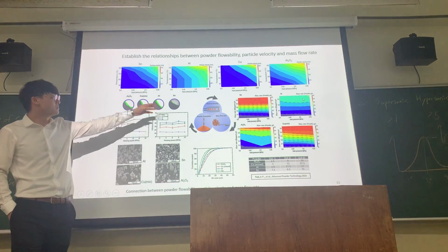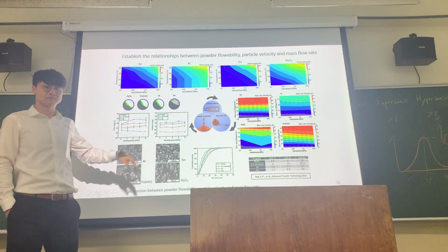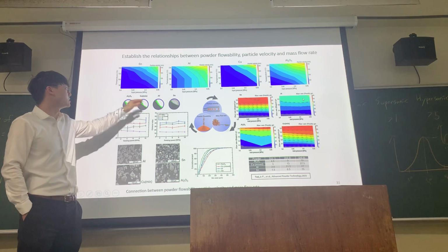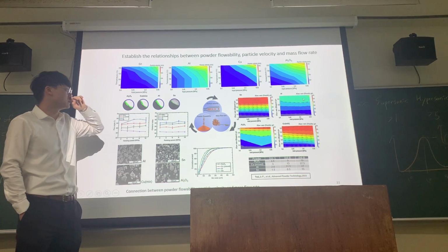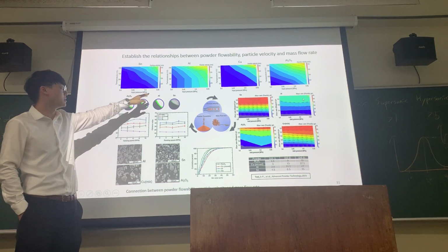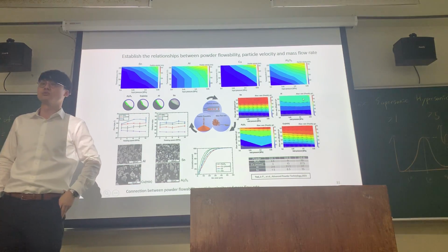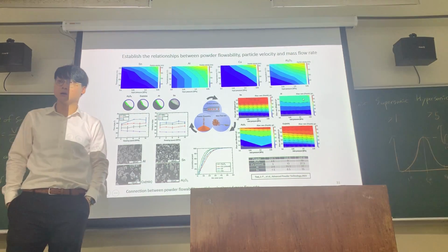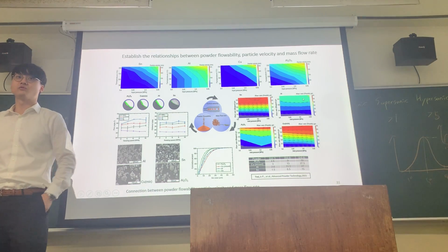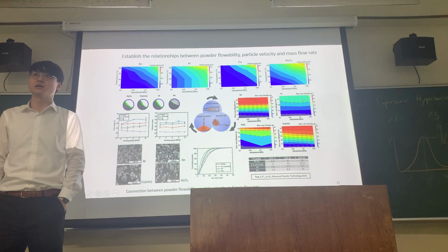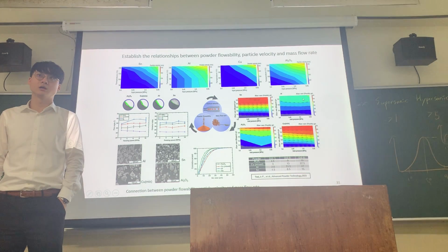And particle velocity over here, as I mentioned. I won't get into detail about all of these definitions, but you can see from these results that the x-axis is the input pressure and the y-axis is temperature. The catch with these is that when you do a lot of these sprays and fix on a certain process parameter, the output velocities are very, very different depending upon what particle you're spraying, right?